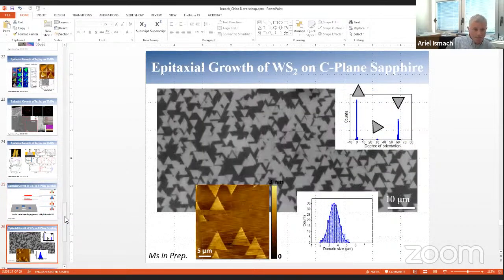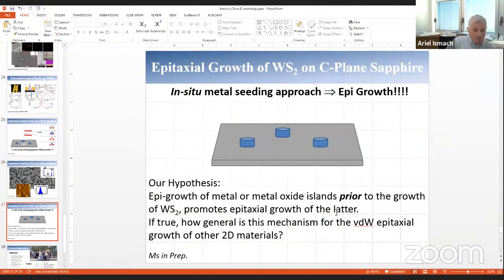You can see here some results. But the important thing is that if you need to have a metal seed which is epitaxially grown on top of the sapphire prior to the growth of the TMD layer, that means that the van der Waals epitaxial growth mechanism that was explained so far, which is the arrangement of 2D materials on top of 2D materials without any commensurability, might not be accurate. So what we are doing these days is trying to further understand this mechanism, but also to ask ourselves how general this mechanism is. Is it general to other 2D materials of many different types, or only to these transition metal chalcogenides?